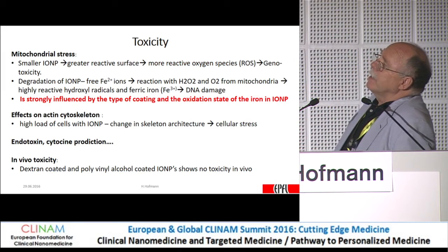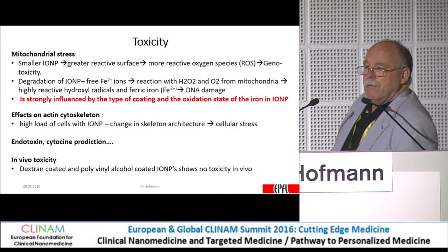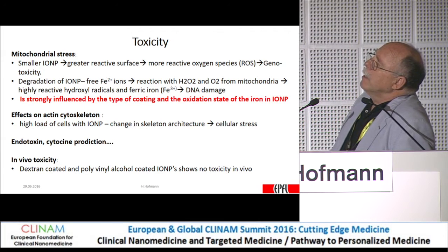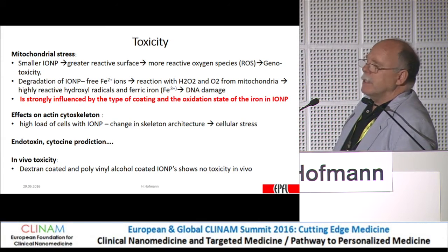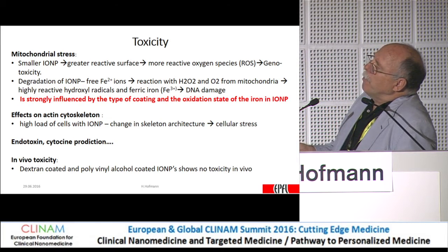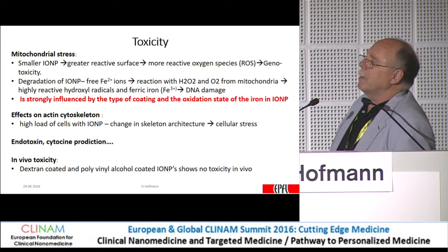Toxicity is similar. There's a lot of investigation regarding toxicity. We can say generally that with small iron oxide nanoparticles we have maybe a little bit more reactive oxygen species and then genotoxicity because of this. The only small problem is that we have degradation of iron oxide particles. And then maybe we have this Fenton reaction and maybe DNA damage, but this does not happen if the particles are in the liver normally.